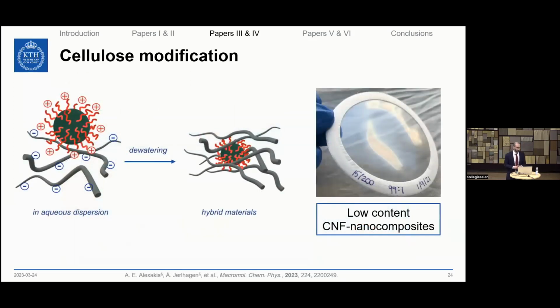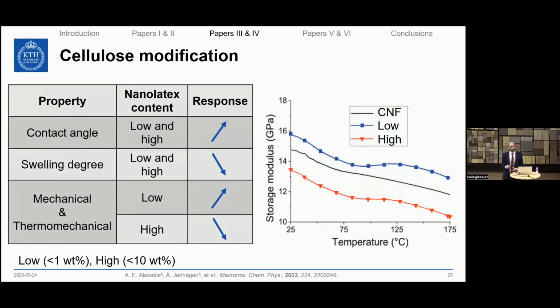In this case, we have used in practice the information that we got from the previous study, working with model surfaces, in order to prepare nanocomposites based on CNF and a low content of nanolatexes. We found out that the contact angle against water of these nanocomposites was increased both for high and low loadings of nanolatexes, whereas the opposite happened for the swelling degree. But what was quite important and interesting to us was that the mechanical and thermomechanical properties of such nanocomposites were increased only when we used a low content of nanolatexes, and they were deteriorated when we increased the content.